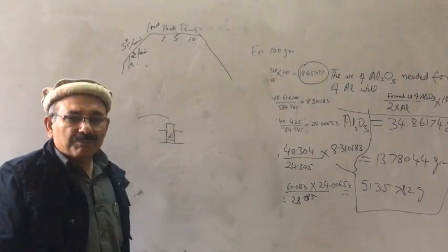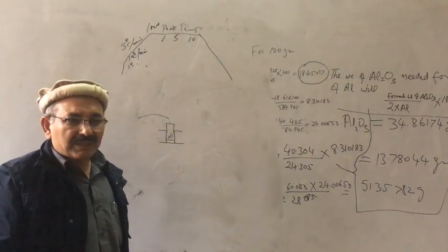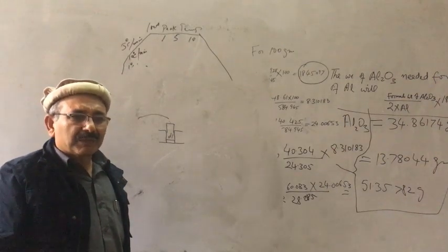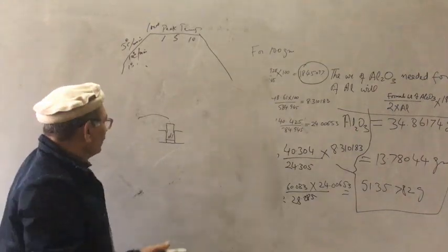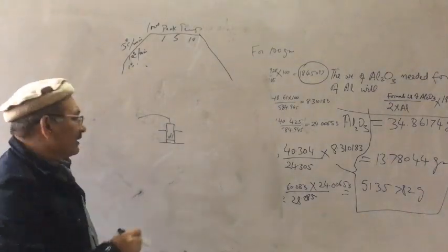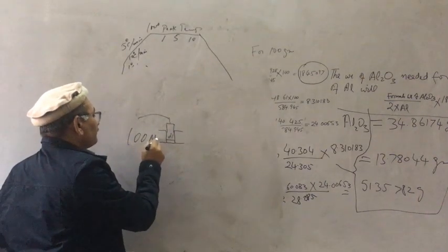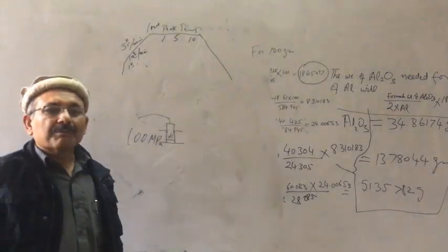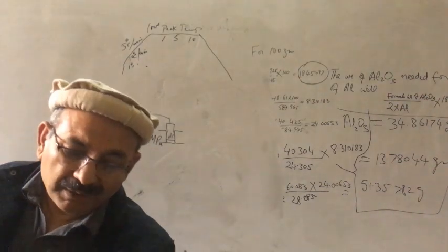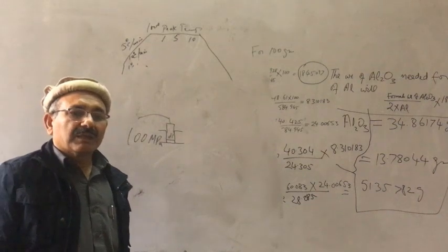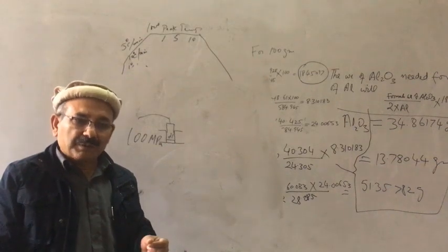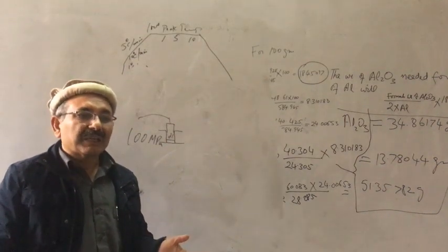There are different forms of presses: isostatic pressing, manual pressing, automatic pressing. So there are different sorts of presses people use around the world. You press the material, keeping the pressure at, for example, 100 megapascal. Again, the pressure is important because it gives the final shape of the pellet. If you overpress a material, when you remove the press, it may crack.